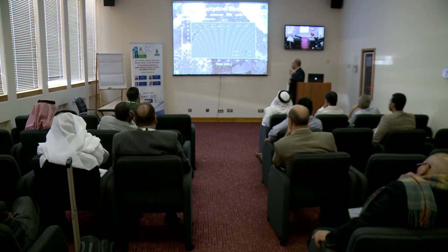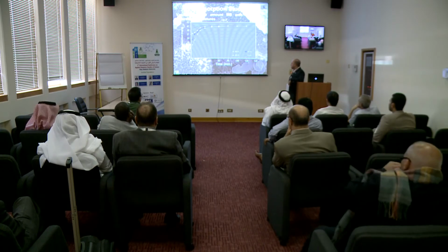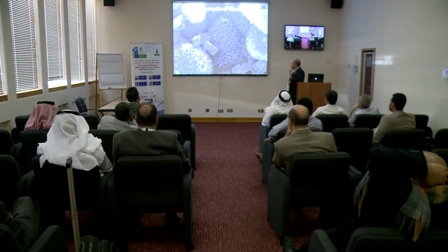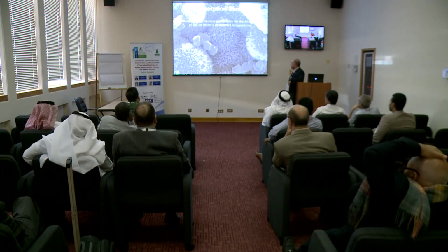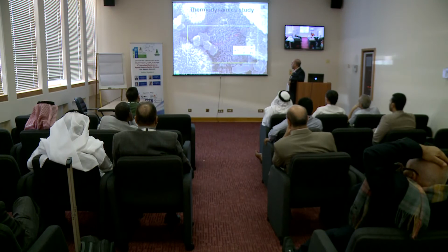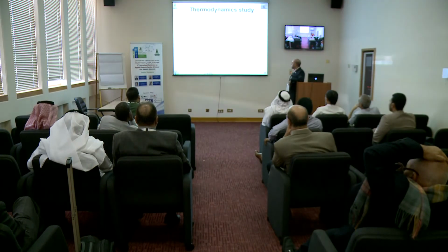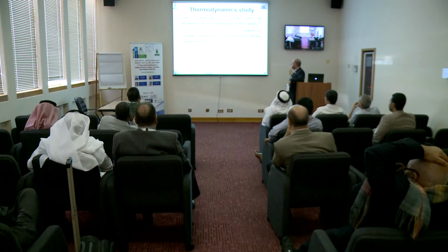Methylene blue is very easy to work with inside the lab, and when we have a new material that we would like to know if it works or not, we usually use methylene blue. The removal of methylene blue using the manganese oxide nanocorals is very fast, within a few minutes, and we studied the removal process from the kinetic point of view. We found it follows the pseudo first order kinetic model. We found the removal process is endothermic in nature, increased by increasing the temperature of the solution. The entropy was positive,